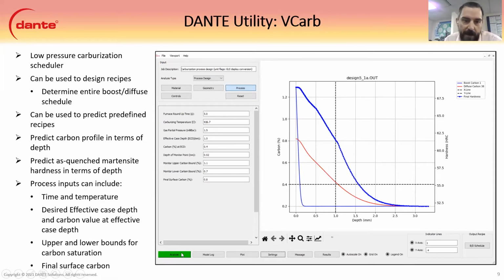And then you analyze it, and then you hit plot, and then you get the plot of the actual thing here. Make sure that's on screen. Move down, there we go. So, oops, go back. All right, and then so actually shown here, I have put indicator lines at the 1 millimeter depth mark and the 0.4 carbon. This was the target. Our final diffuse here puts us a little bit above that, which is kind of good. You always want to be a little over than a little under, right? And that shows exactly what it would be. And this would be the hardness of the as quenched Martensite at that point.